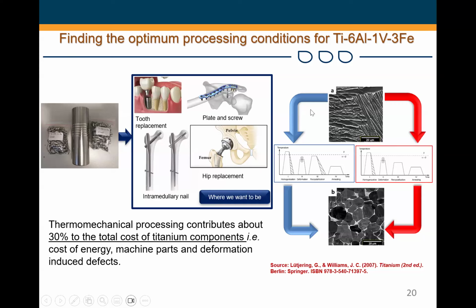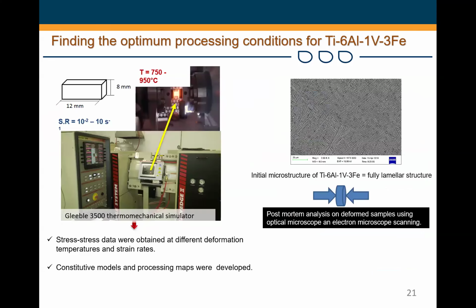I had shown you previously that the microstructure of the cast material was a fully lamellar structure. But for thermomechanical processing, for ease of processing, we always like a rounded structure or an equiaxed microstructure. And for you to move from A to B, you can use either the red path or the blue path. But if you count the number of steps, it's 1, 2, 3, 4, 1, 2, 3, 4. So could we find a way to reduce this to one single step and see whether it's possible to start having some rounded structure rather than having an elongated structure or a lamellar structure? And that is what we did using our Gleeble 3500 thermomechanical simulator.